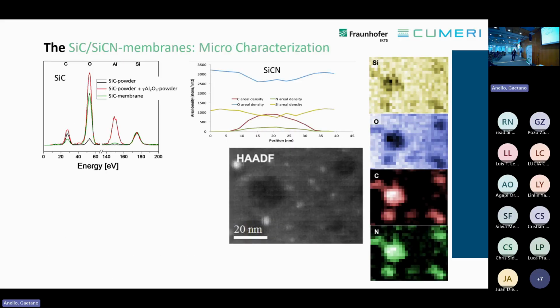Then we made a microcharacterization of the material, of the silicon carbide as well as of the silicon carbon nitride. And what we have seen in both cases is that we found a lot of oxygen. This was really surprising. If you look at the EDX mapping on the right-hand side, you can see that oxygen is more or less everywhere, while the carbon and the nitrogen are only in some dots. So practically, it seems that it's more or less a silica membrane with some silicon carbide or silicon carbon nitride dots, and the dots have a size of 20 to 30 nanometers, very small dots. This was a little bit disappointing.